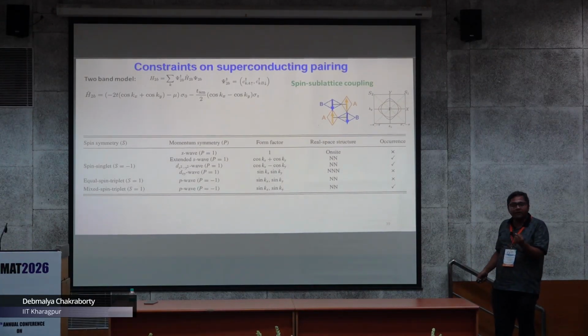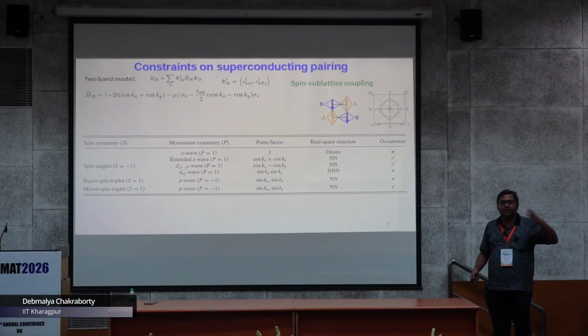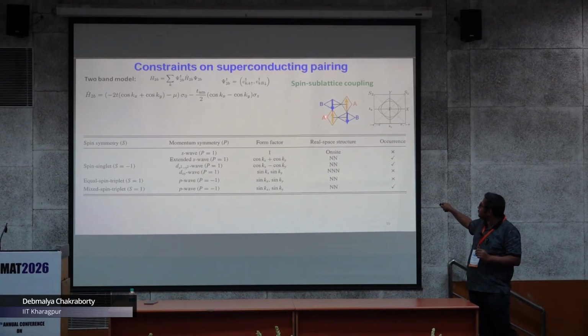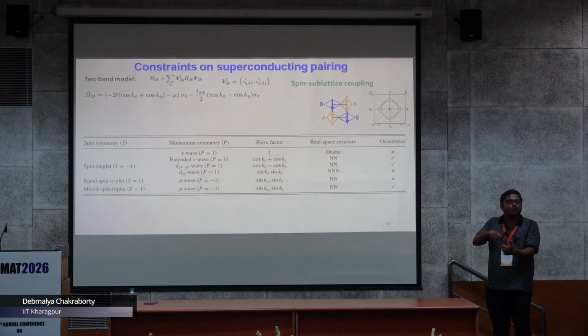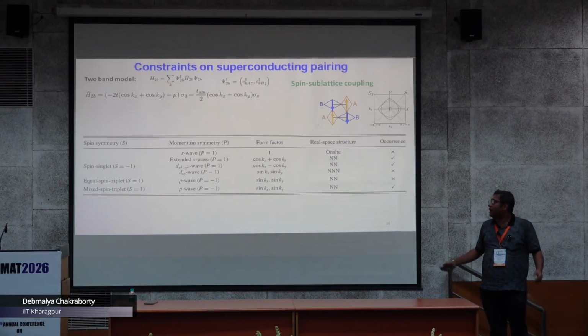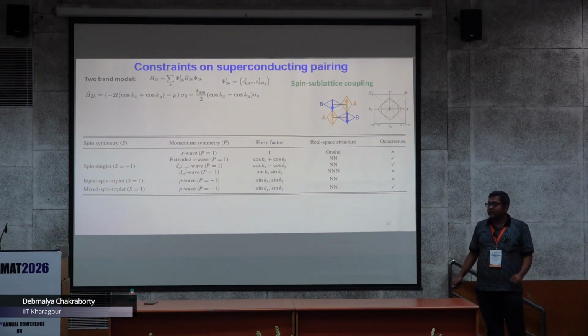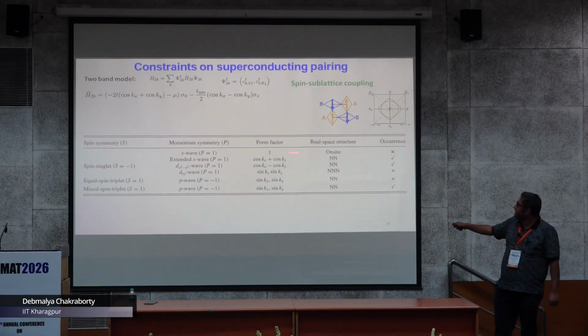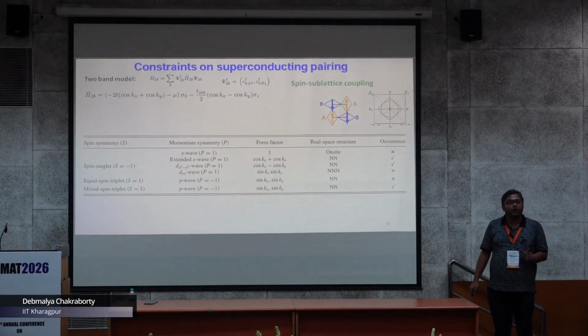If we think of S wave, that I was saying, okay, by hand let's say we have S wave, we cannot, because S wave would need on-site up-down pairing. There is no down band near this A side. Similarly, there is no up band near B side. So this spin singlet S wave pairing is not allowed at all.